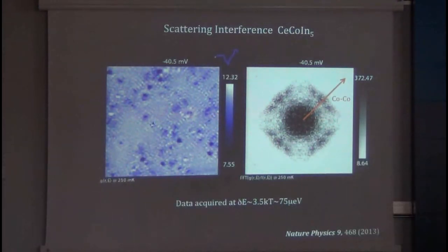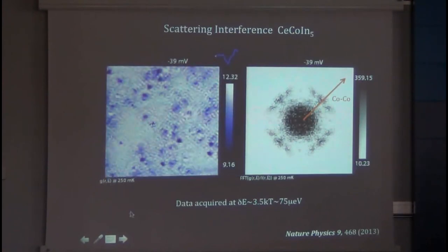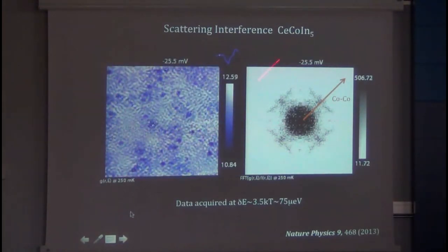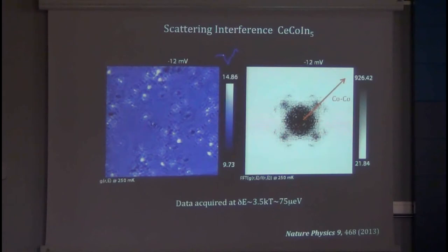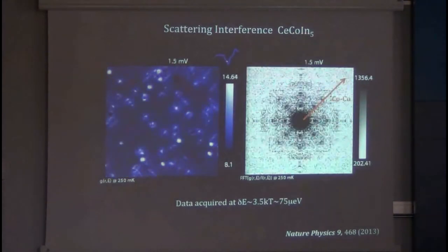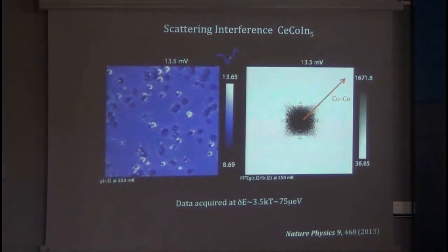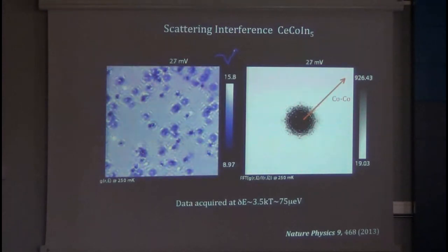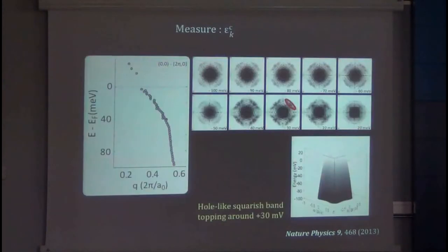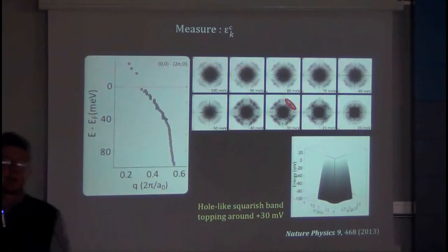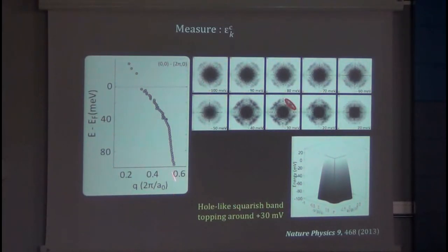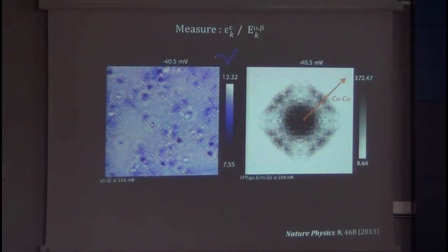These are wave function images and Fourier transform images for cerium cobalt indium 5. Very little happens because it's a light band, but there's the heavy band. It's just a couple of millivolts wide. Very little happens again because it's a very light band. You can use this information to track the light band in momentum space by following the features in that movie. And it's a hole-like squarish band, and it actually ends a little bit above the chemical potential.